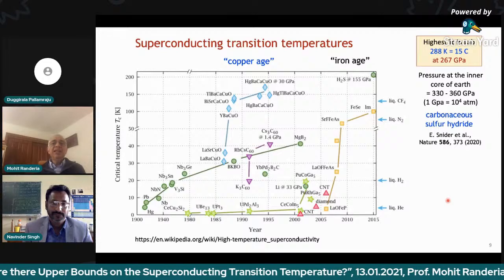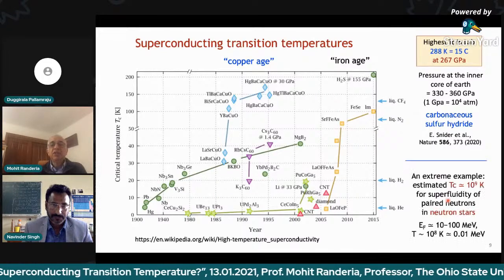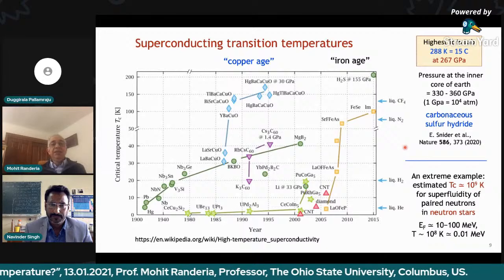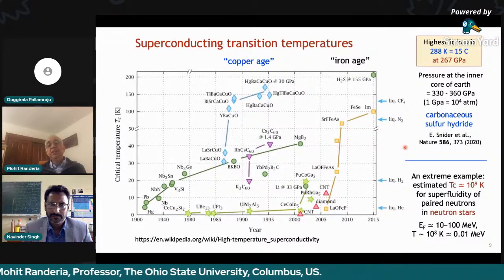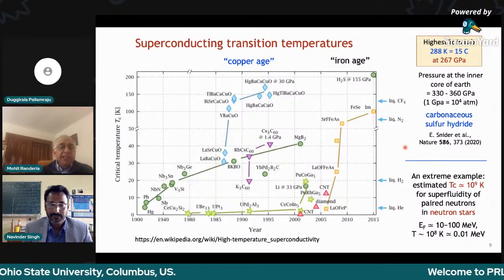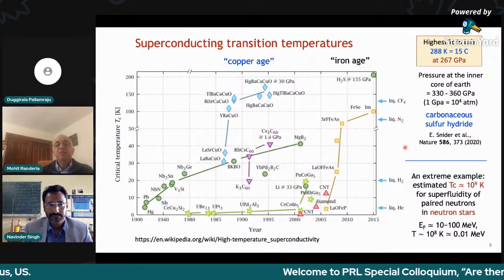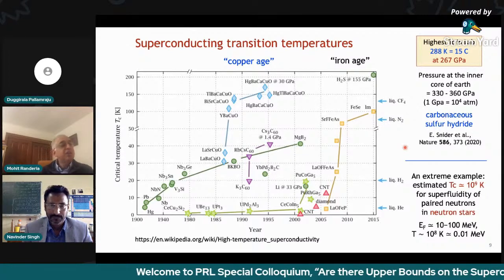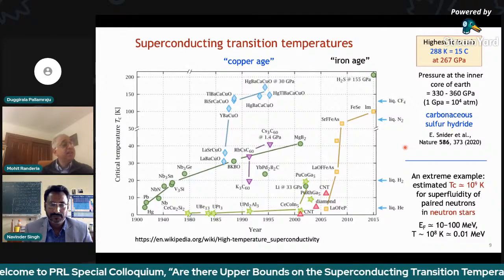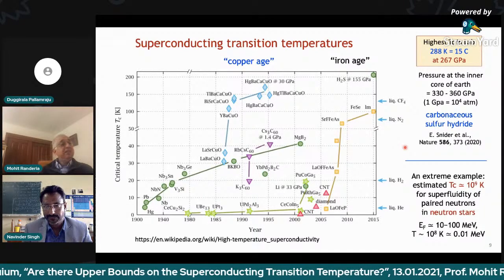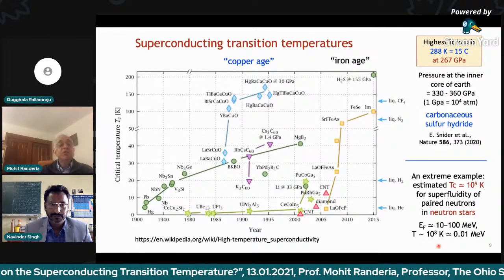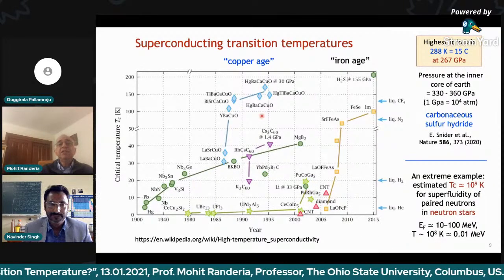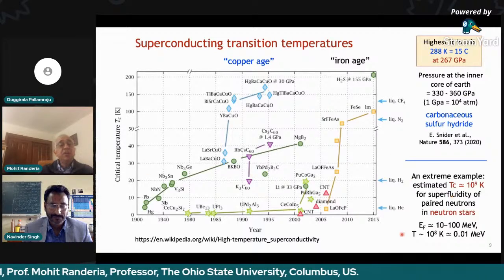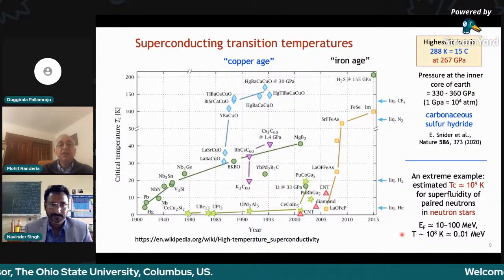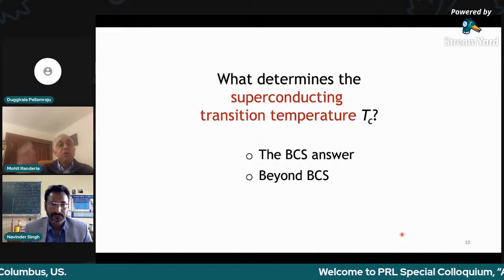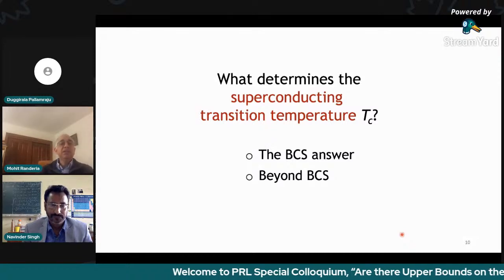Now, while we are talking about superconductivity in extreme conditions rather than ordinary laboratory conditions, an extreme example is that the estimated TC for paired superfluidity in neutron stars is like 10 to the 9 Kelvin. Of course, all the scales there are humongous. Instead of having a Fermi energy which is, say, of order a volt or 10 volts, it's actually 10 to 100 mega electron volts, okay? And the room temperature of a neutron star is also 10 to the 8 Kelvin. So anyway, this seems to suggest that TCs can become extremely high, and one is most interested in understanding how high TC can be in a lab, but even more importantly, one should ask what determines the superconducting transition temperature.